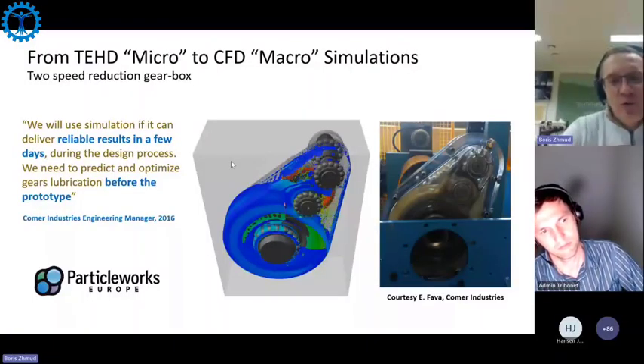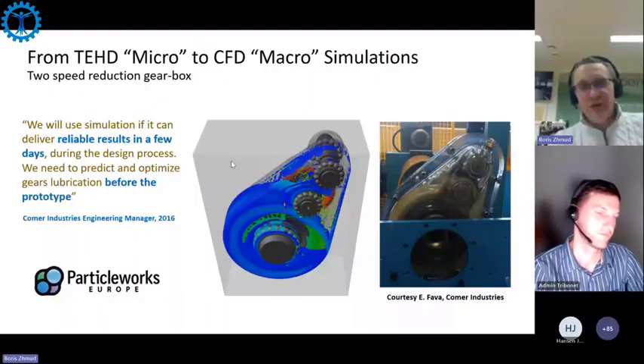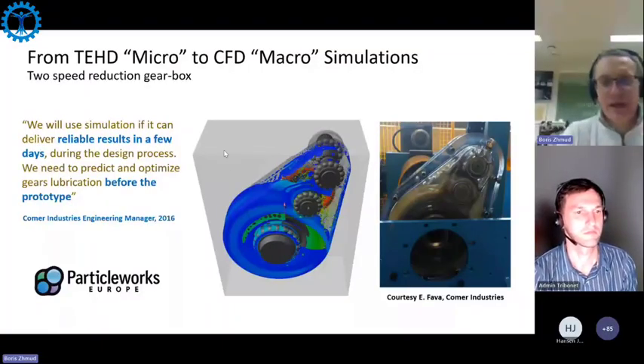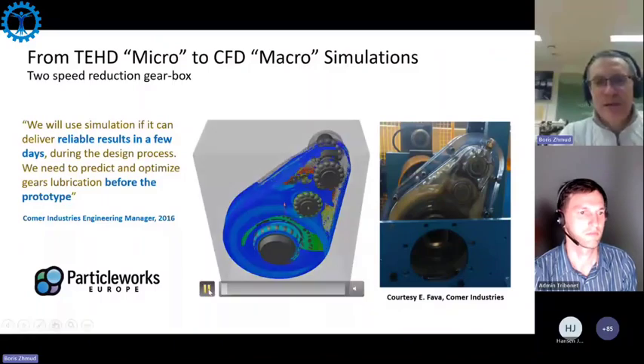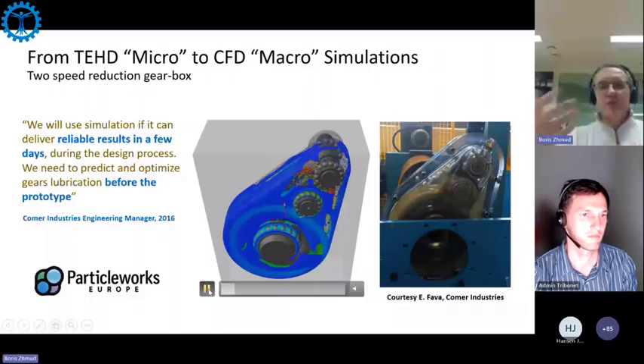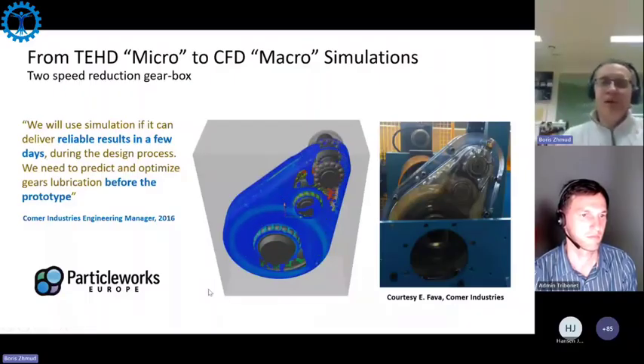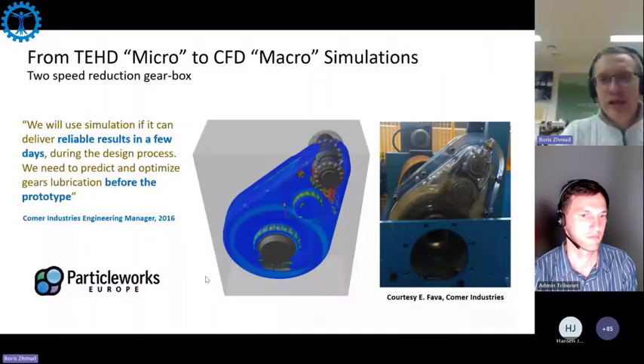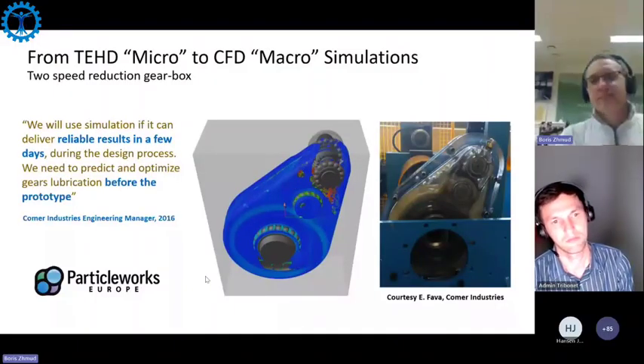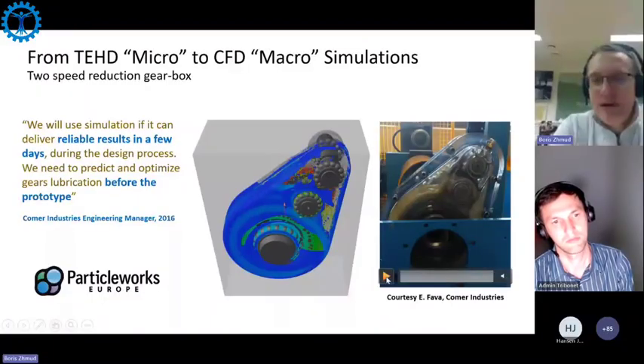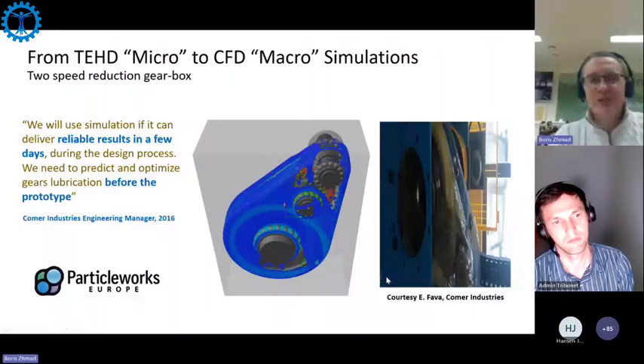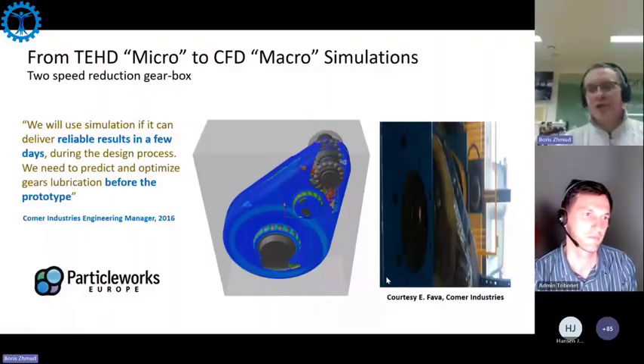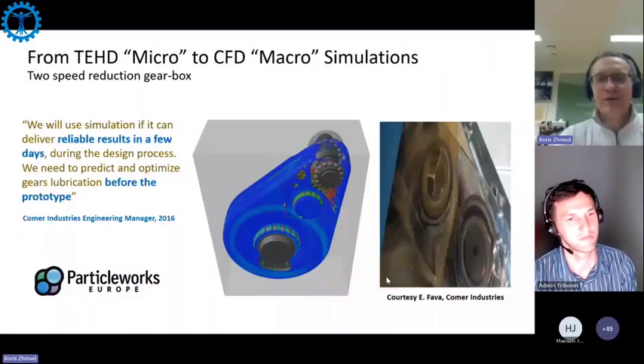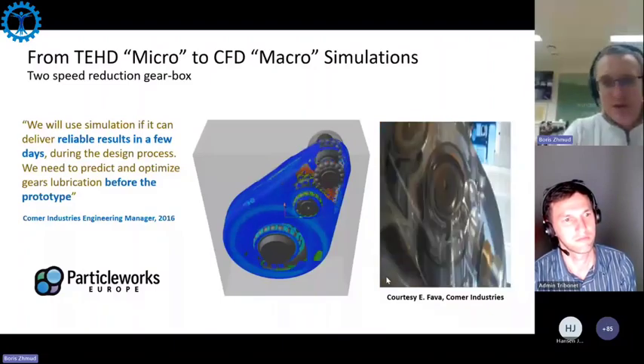So we can go to the simulation of the whole appliance, not only a simulation of your contact line in gear meshing, but you can simulate the whole appliance. So you can simulate how your lubricants will move in the gears. You can simulate temperature maps, stress maps, and so on. So it's a very powerful simulation tool. And even more important, those simulations are usually verified or validated by real experiments with real fluids, which shows that simulations have very good predictive power. It's pretty remarkable how much progress was made on the simulation side over the last decades due to the increase in computer power.